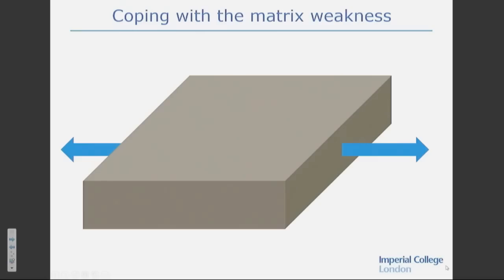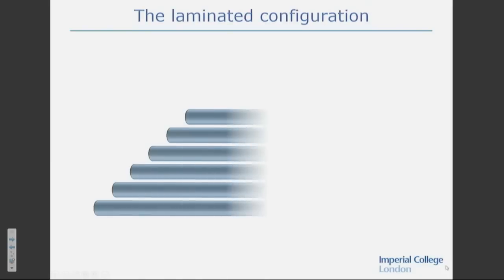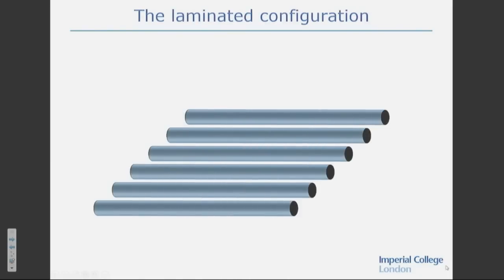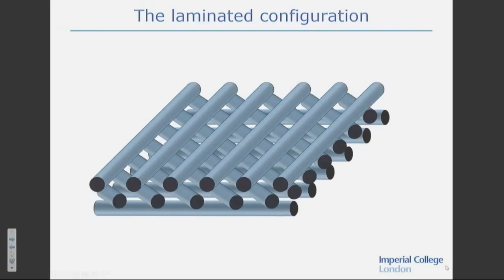Well, think about this. Here's a piece of composite. It's got some load like this, and maybe some load in the other direction there, and so on. And it might have a complex pattern of loads on it. What we do is make a laminate. And the laminate has fibers running in various directions to ensure it can resist all those applied loads without transverse failure, transverse to the fiber failure. Of course, this is still set in the matrix. And the laminate, it's called a laminate because it consists of layers, of course. And I can show you the layers structure there. Okay. So this is the laminated configuration. And this gets over this in-plane weakness.